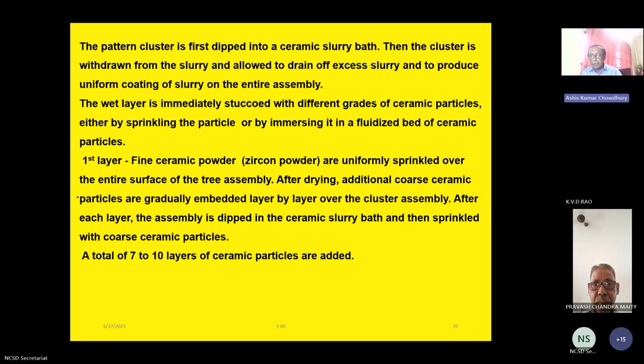of the tree assembly. After drying, additional coarse ceramic particles are gradually embedded layer by layer over the cluster assembly. After each layer, the assembly is dipped in the ceramic slurry bath and then sprinkled with coarse ceramic particles. A total of 7 to 10 layers of ceramic particles are added to form the total layer. This thickness depends upon the weight of the component, particularly, and density of the material. These are the two factors that have to be decided.